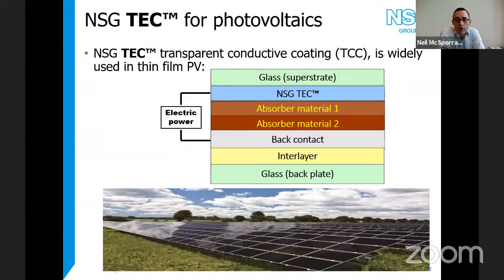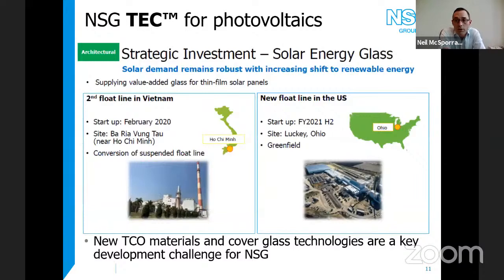One of our leading products, though, is our NSG Tech product for PV. So when you're using essentially thin film photovoltaics, the first material you need is a transparent conductive coating, and we put down that in very large area for thin film photovoltaics. Basically, we're building the first part of the photovoltaic device on glass. And we make huge amounts of glass using this technology. So at this point, we have 4 float lines entirely dedicated to supplying the thin film photovoltaic market. So that's a huge amount of glass supplied globally.